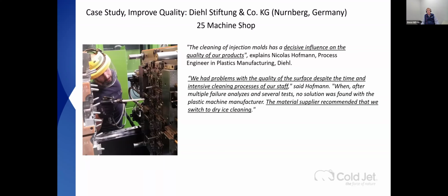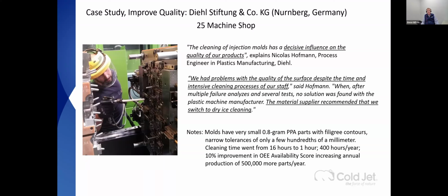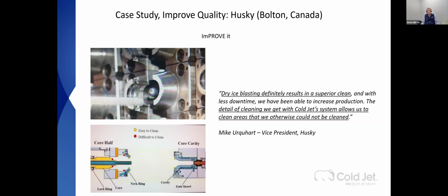This is a guy who had all kinds of problems with parts. They couldn't figure it out. The plastic machine manufacturer couldn't figure it out. It was their resin supplier who said, if you try dry ice cleaning, these guys are molding some very small parts, and they went from cleaning at 16 hours to 1 hour. That's 400 more hours a year they got back, a 10% improvement on their OEE availability score, 500,000 more parts per year, just because they switched over to dry ice. That's improved cleaning quality.